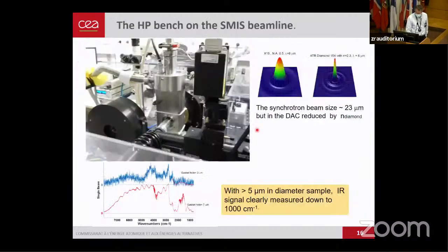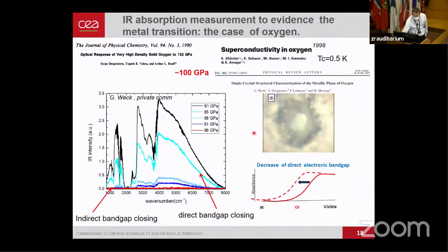And what I showed is that for oxygen, when we see the absorption of the intensity in the far infrared, the conductivity measurements in this range are even greater than 10 to the minus 4 ohm meter. So it's not very conducting, and still oxygen has not reached its phase transition. But if there is a semi-metal, you should see something for reasonable conductivity smaller than 10 to the minus 4 ohm meter. You should see a decrease here.